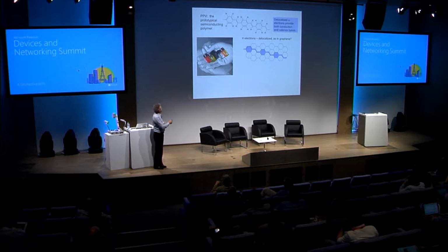Now, there's a huge amount of chemistry, and I decided that chemistry is one thing not to put into this presentation. But essentially, you can chop and change. You can put nitrogen atoms or sulfur atoms in. You can put oxygens in. You can attach electron withdrawing or electron donating groups onto the side of the conjugated molecule. So you can tune everything. And it turns out that as engineerable semiconductors, organics are fantastic. There's much more we can tune than if we're stuck with the inorganics, where apart from silicon and the 3-5s, there isn't a lot that really works.